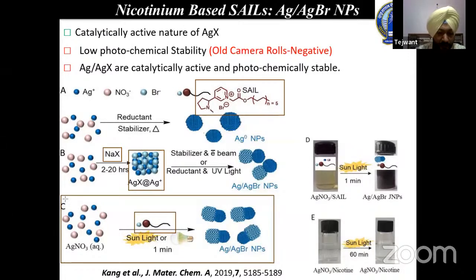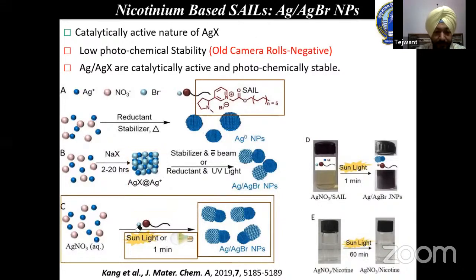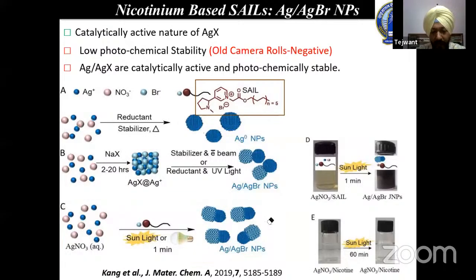Now in the aqueous silver nitrate, you add ionic liquid, shake it, and keep the solution under sunlight or visible light for just 1 minute. One can see the formation of nicely placed silver bromide Janus nanoparticles. So now you can see we have reduced the time from 2 hours to 1 minute. You can reduce the number of chemicals. We have not used the silver halide, we have not used the extra stabilizer, we have not used the electron beam. Because of all these credentials, this work was published in Journal of Materials Chemistry in 2019.